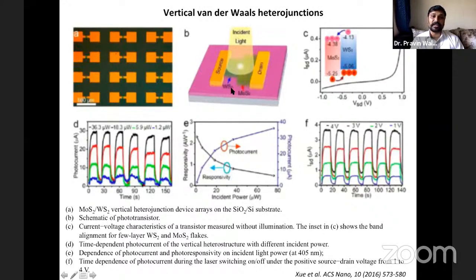Here you see MoS2 and WS2, where a vertical junction has been formed. For this vertical junction, you see the band diagram in the inset here, and in the dark current, you see the I-V characteristics over here. So this is the dark current. As soon as the light is illuminated at different powers, as you increase the power of illumination, you will find the photocurrent generation is quite a bit higher, right? So a large photocurrent is generated, right? And this on-off ratio is improved with respect to the power.